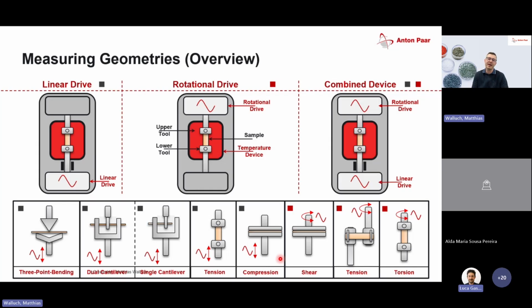For example, if we have a very stiff material, we have 3-point bending because we just have a sample that is placed here. We apply normal stress here, and we do some movements upwards and downwards, and then we can apply a certain temperature, and we see transition temperatures of the material. Of course, if the material would be too soft, then it would not be possible to bend.